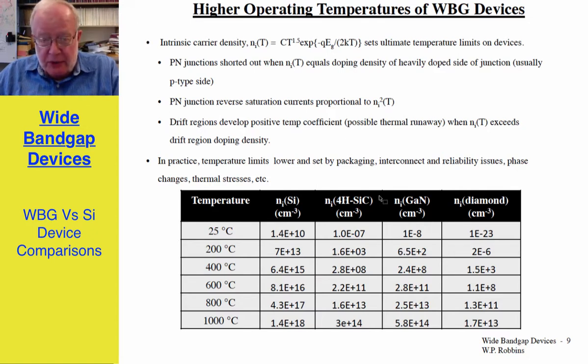Higher operating temperatures of the wide bandgap devices are basically due to the fact that wide bandgap means that the intrinsic carrier densities are much smaller. Here I have a table of different junction temperatures, and for each of the 4 major materials that we're considering, I show the intrinsic carrier density. And even at elevated temperatures, as high as 1,000 degrees, silicon carbide has an intrinsic carrier density of 3 times 10 to the 14th. Diamond is about 1.7 times 10 to the 13th, whereas silicon is 10 to the 18th.